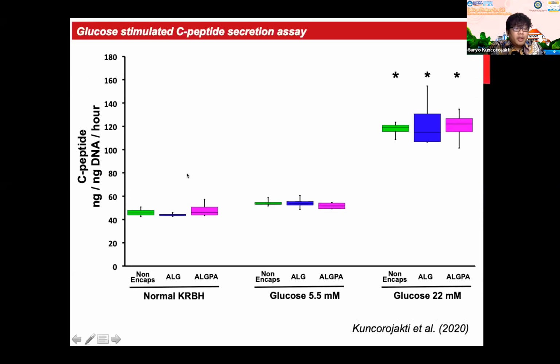And we also did the in vitro evaluation regarding the function of encapsulated mesenchymal derived IPC by using a glucose-stimulated C-peptide secretion assay. The results of these experiments were compared with the initial condition of the mesenchymal derived IPC, meaning before encapsulation. At day 14 post-encapsulation, the results show that C-peptide was secreted by mesenchymal derived IPC in both platforms, in alginate and also alginate pluronic based encapsulations.